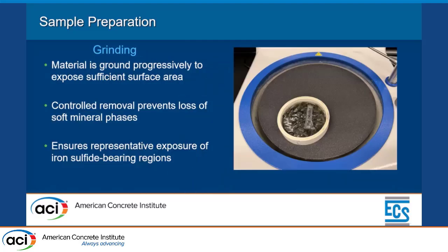So we're first going to grind the material, starting with something really coarse. An 80 grit silicon carbide typically is used on the wheel to do quick and controlled grinding. So what we're trying to do is grind through all those grains. For the sand, we can have hundreds of grains that we're going to cross section.